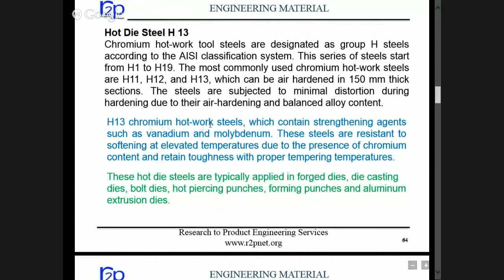H13 is a chromium hot work steel, which contains strengthening agents such as vanadium and molybdenum. These steels are resistant to softening at elevated temperature due to the presence of chromium content and retain toughness with proper tempering temperatures. So the examples are typically applied in forging dies, die casting dies, hot piercing punches, forming punches, and aluminum extrusion dies. So wherever the metal is heated while working, H13 is used for making the dies.